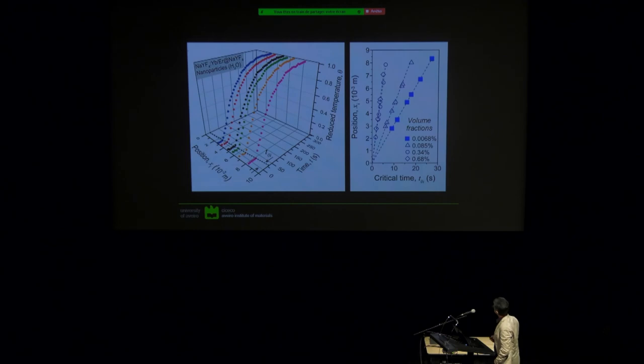And by doing that, we produce plots like this, so this is the position, and that's the time of the experiment. And so, for example, here, position 8 millimeters from the heater, we had to wait about 45 seconds or whatever, until we started getting emission spectra which changed, and we could convert that into temperature. And temperature was rising with time until it plateaus. Okay? Then we moved to another position, and we did it again.